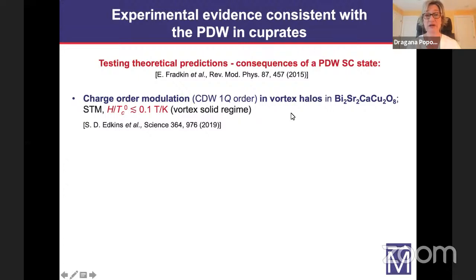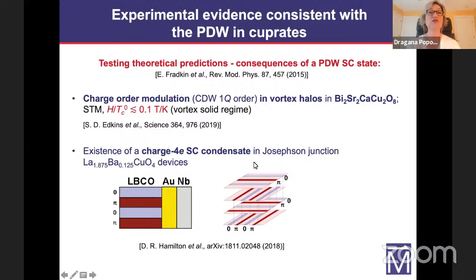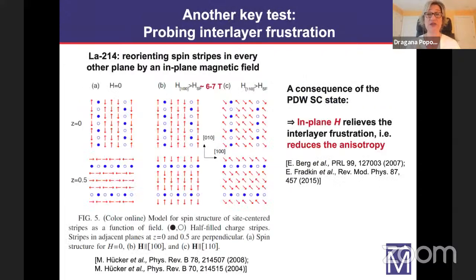So this was found by STM in BSCCO, where they applied a relatively small magnetic field such that the material was still in the vortex solid regime, but the magnetic field was sufficient to suppress the uniform superconductivity in vortex halos and to allow the pair density wave order to emerge. Another prediction was for the existence of the so-called charge 4e condensate, and this was also observed recently in the group of Dale Van Harlingen in Josephson junction devices based on LBCO at 1/8 doping. And yet another theoretical prediction was to actually probe the interlayer frustration by applying a suitable perturbation.